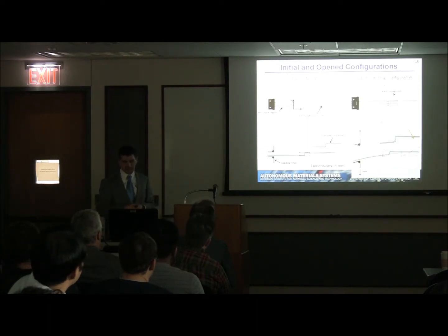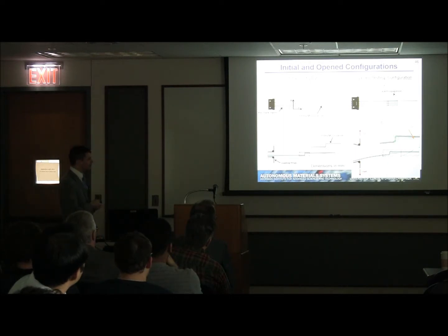And they traverse below the crack plane at one point, and then at roughly 25 millimeters away from the pre-crack, there's a kind of an upswing of this channel through the midplane of the specimen before it then leaves the backside. And so how that looks when we're actually testing the sample and as the crack is propagated is, again, top view, side view. After the crack is propagated through the sample, we actually pierce the microchannel at a location which we know, and which we can call the piercing point.